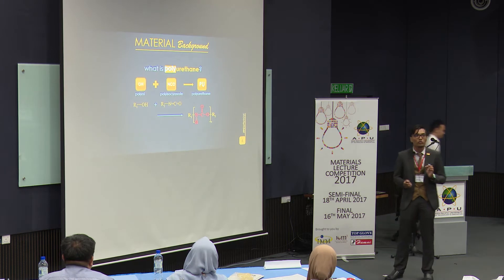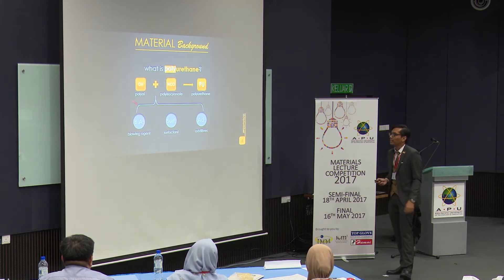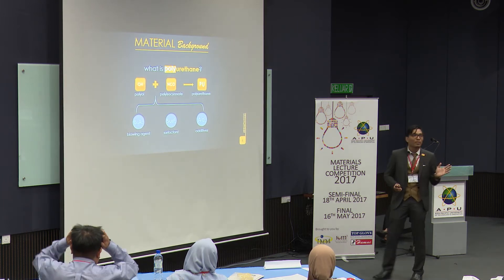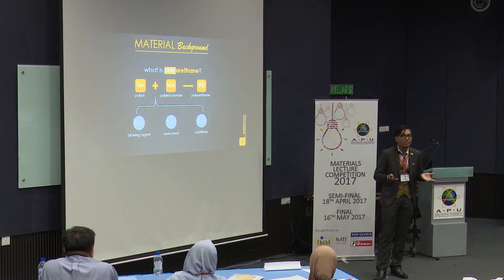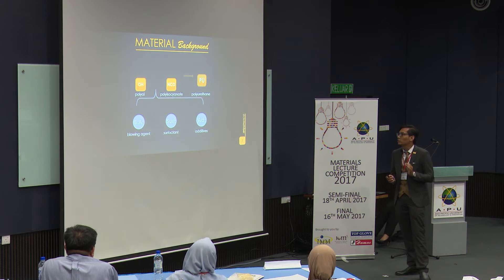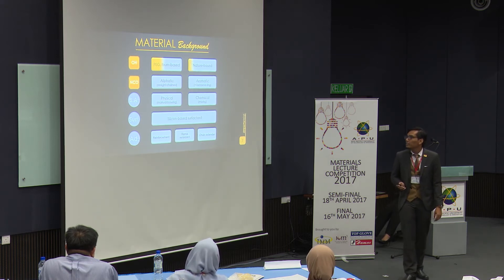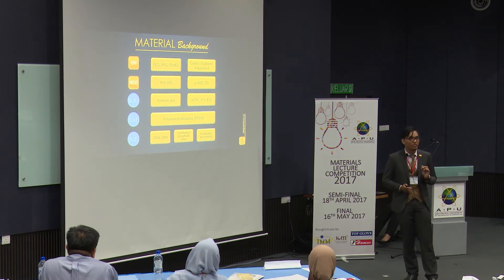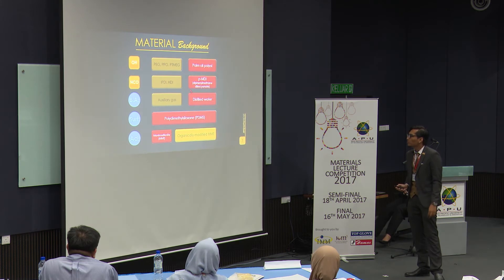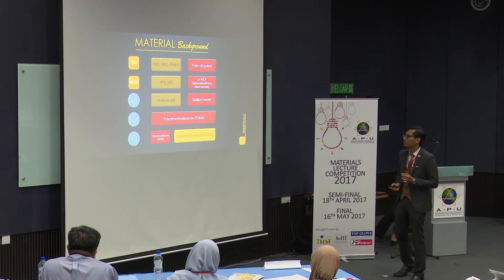In industry, other substances are added to obtain a better foam. For instance, a blowing agent is added to induce the formation of bubbles inside the foam and to prevent the foam from collapsing. Additives can mean anything — carbon nanotubes to enhance mechanical strength, or flame-retardant materials to make the foam fireproof. For the purpose of this presentation, I'm going to focus on palm oil polyol, PMDI, distilled water as the blowing agent, polydimethylsiloxane as the silicone surfactant, and also montmorillonite — an organically modified nanoclay — as the additive.